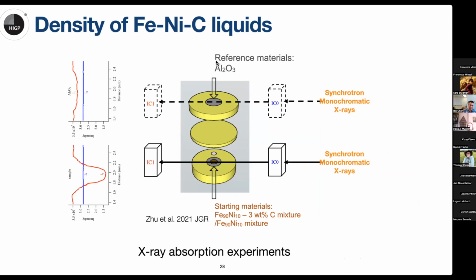The X-ray absorption experiment is set up like this. We can focus on the reference material, which is alumina. Using the X-ray absorption technique, we can see the absorption profile of the alumina phase, which can be calibrated to the density of alumina at those PT conditions. We also collected, focused on the sample, the X-ray absorption coefficient profile across the sample. And then we can calculate the density of the iron nickel carbon liquid at high PT conditions.